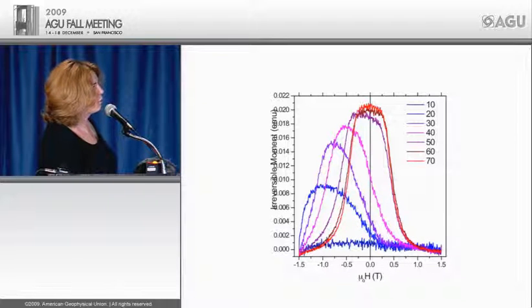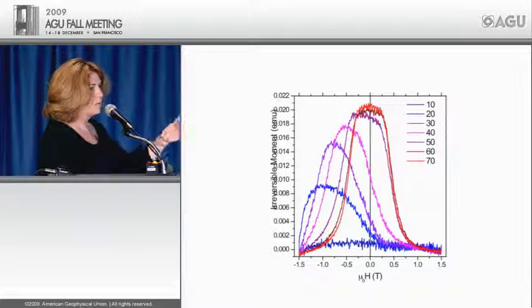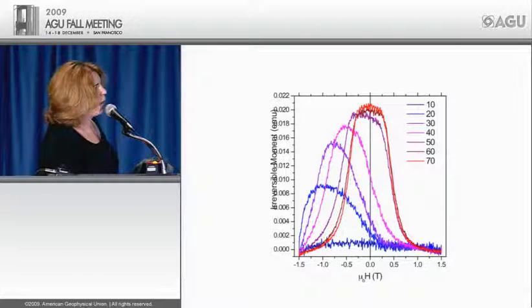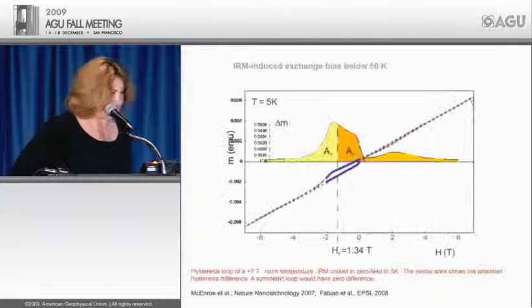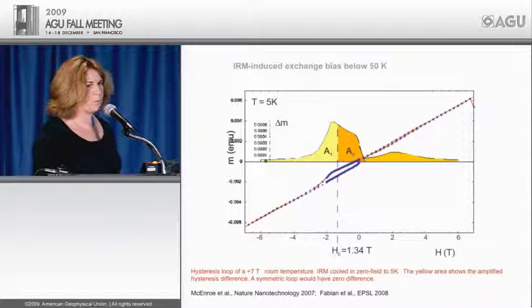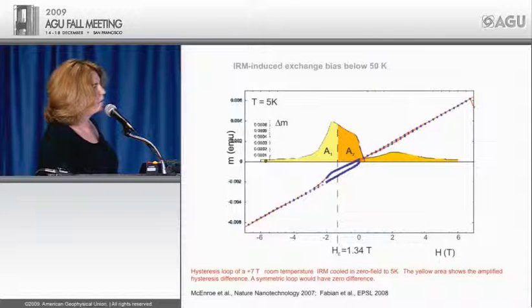So here we're just looking with temperature at the center of that loop. So at 60K, we're centered, and as we go down temperature, you can see the loop continues to shift further and further. Now, between 60 and 50, what happens is ilmenite orders. And here, the ilmenite is only at the subunit cell size. As soon as that ilmenite orders, we start to have a shifted loop. Now here, those loops were minor loops. So we had to go up to higher fields to measure this loop. We went up to 7 teslas. And the shift of this loop here is 1.34 teslas.